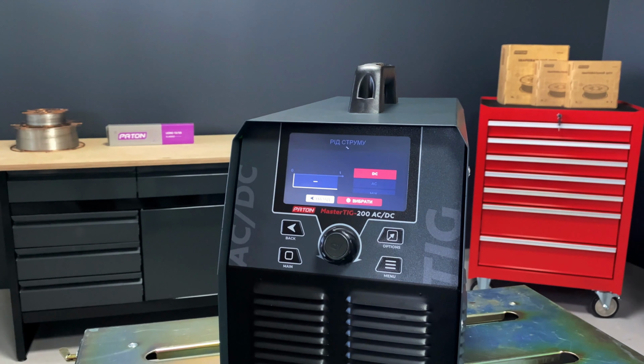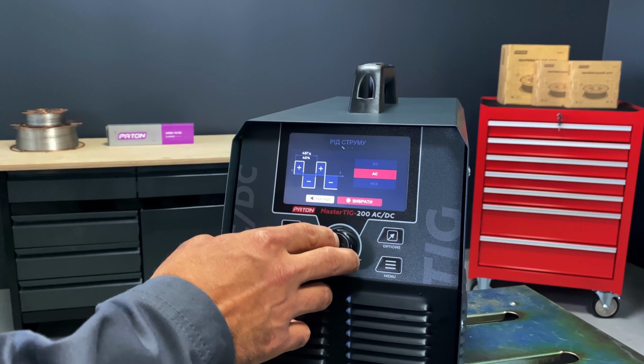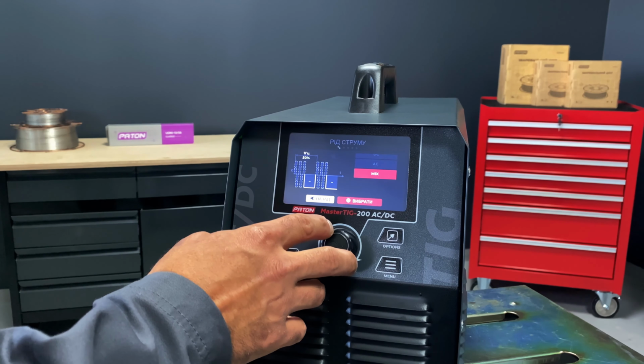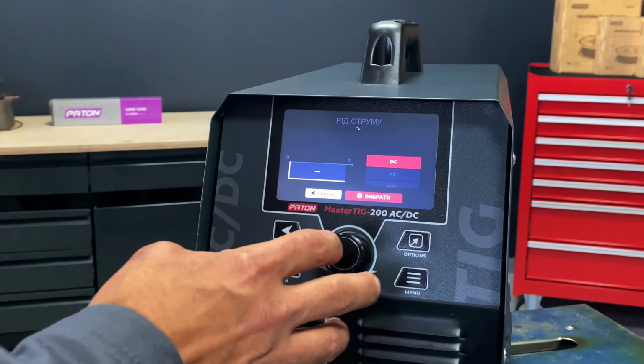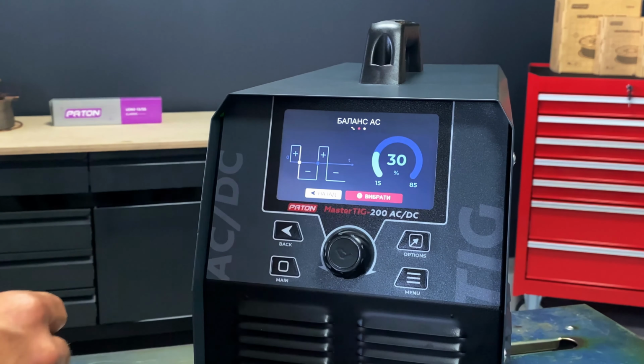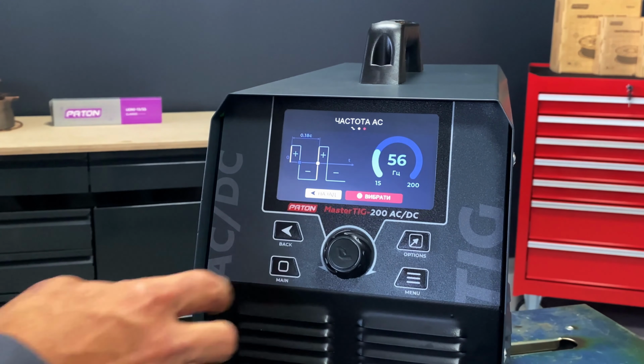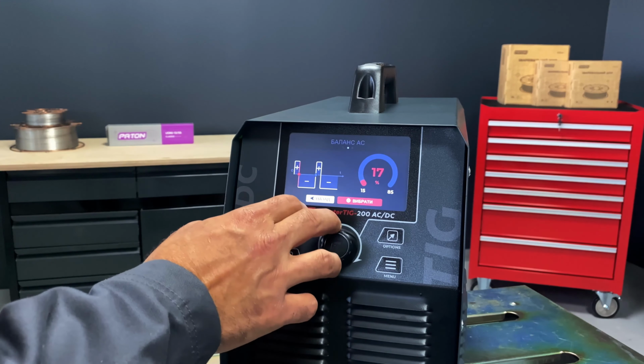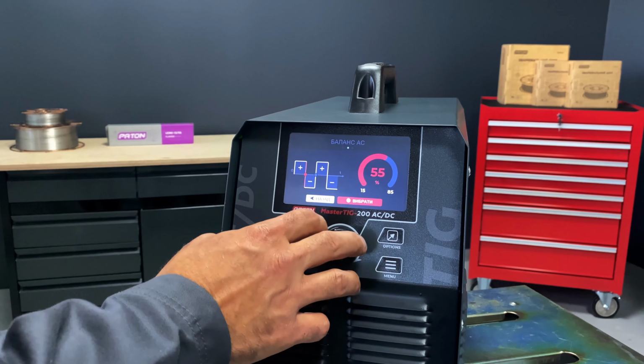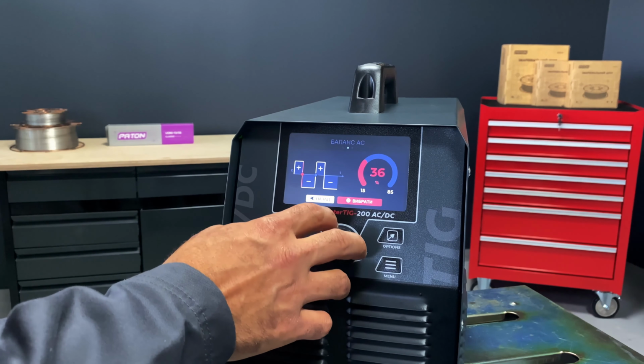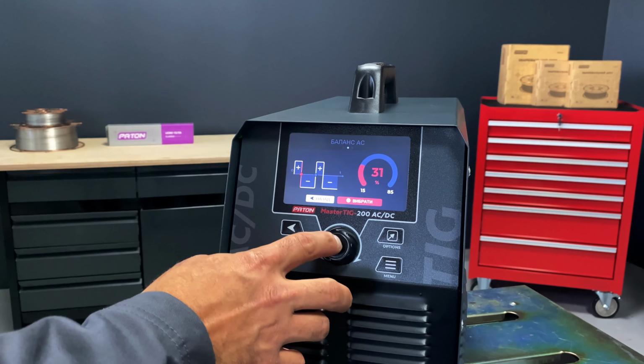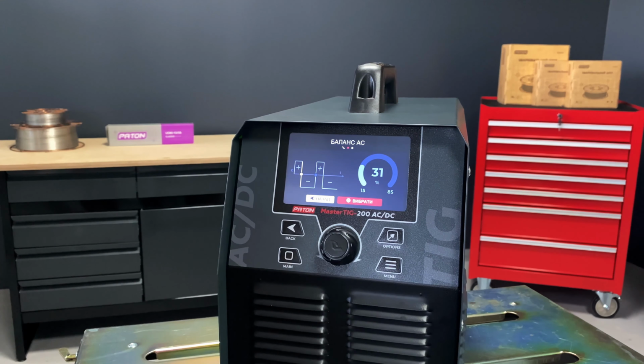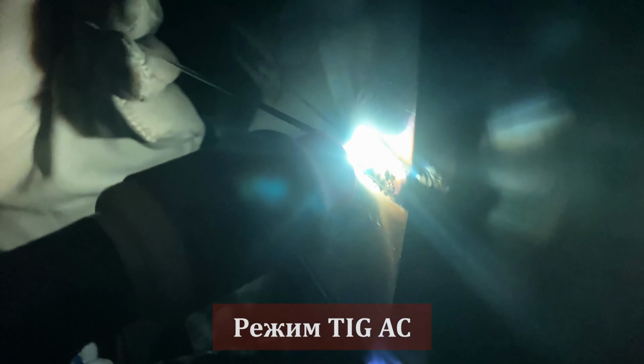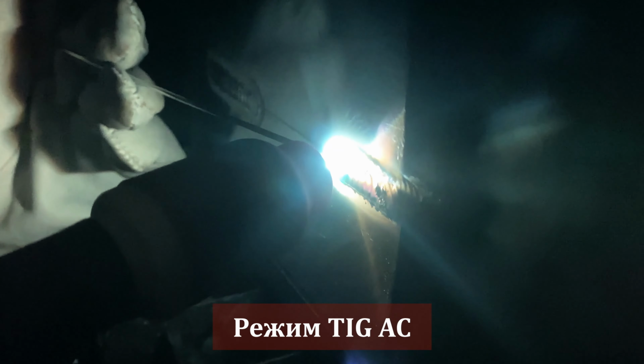Current type. There are three options available: direct current, DC, alternating current, AC, and a combined mix mode. In AC mode, two main parameters are available: balance and frequency. Balance is the ratio of positive to negative polarity time. Positive polarity is responsible for cleaning the weld area from the oxide film, while negative polarity determines the depth of metal penetration. The more time the machine operates in positive polarity, the more effectively the surface is cleaned, but the penetration depth decreases. And conversely, more negative polarity provides deeper penetration, but reduces the cleaning effect.